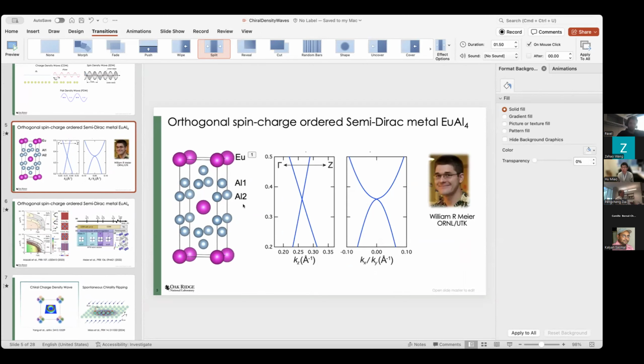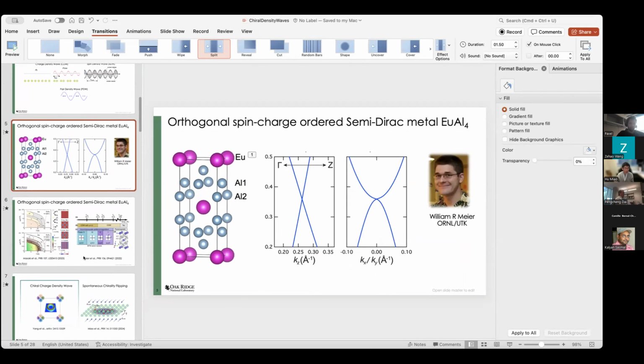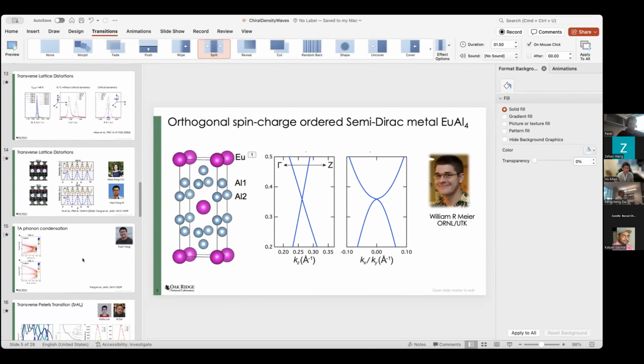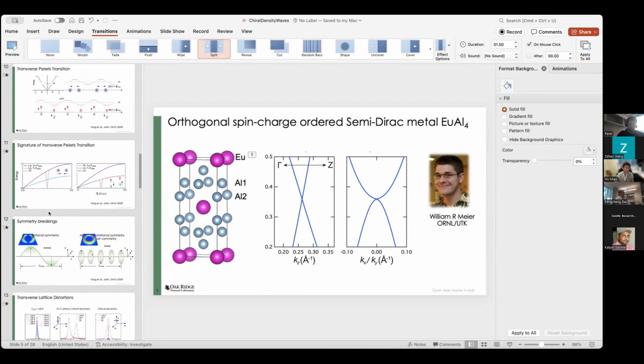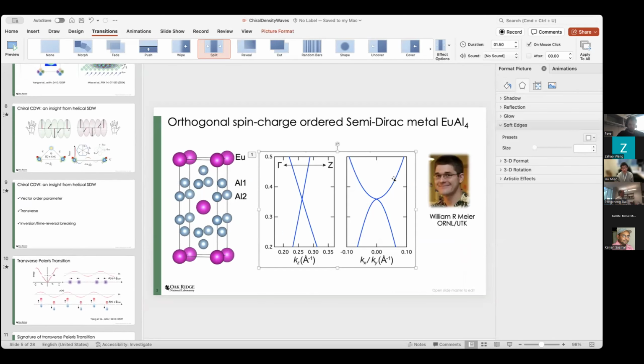It's not very 2D. We actually have DFT calculations. Here's the DFT calculation. It forms a Dirac point, so it's highly dispersive along the c-axis. Have you done measurements where you dope it with gallium, to see whether this chiral CDW changes? Yes, we did. We had beam time.